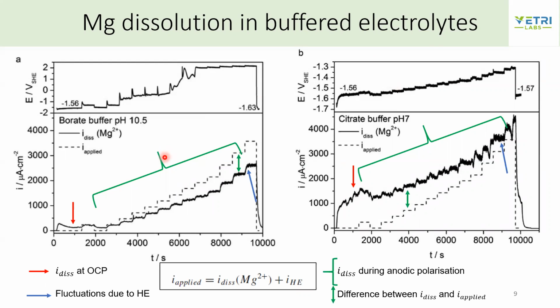I think this is again just the magnesium dissolution current and not the hydrogen evolution. So they took two different solutions, one with a borate buffer of pH 10.5 and the other with a citrate buffer of pH 7. And they tried to increase the steps after an OCP.